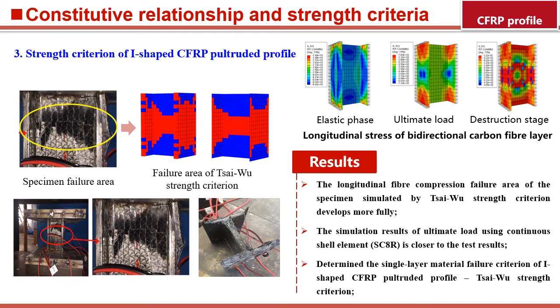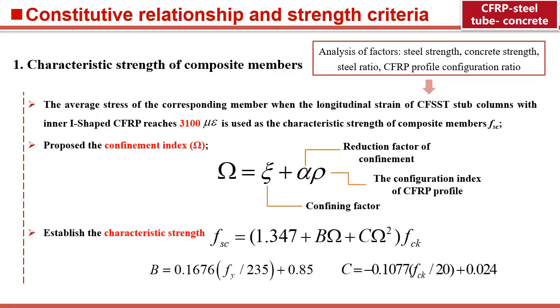Combined with the finite element analysis and experimental results, the strength criteria of the profile are determined, which has laid an important theoretical basis for the analysis of the following members. Regarding the constitutive relationship of composite materials, we define the strength criteria of the composite materials through the corresponding characteristic points at each stage of the strength failure process. Then, on the basis of proposing the double composite effect coefficients, the character value, proportional limit, elastic modulus, tangent modulus, and the other indexes of the composite materials are established.